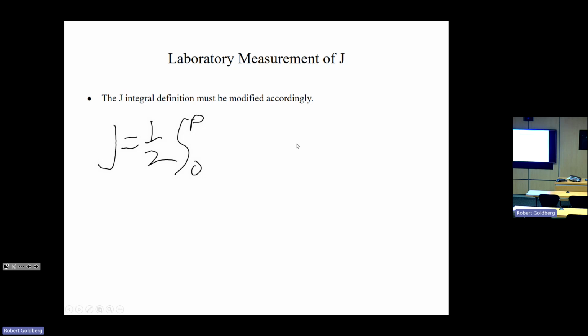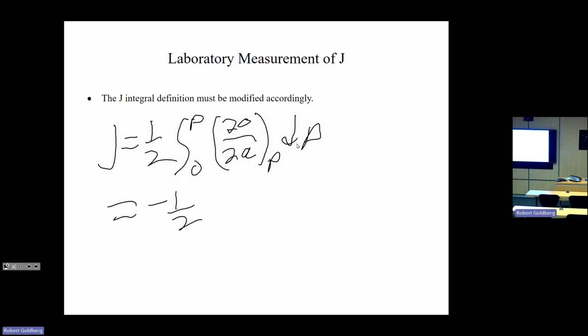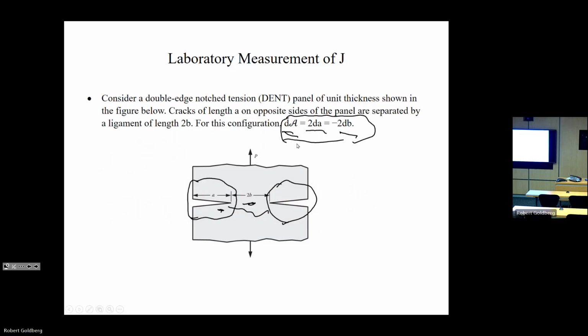So integral from 0 to the current value of applied load of the derivative of the resulting displacement with respect to crack length, for the fact, specifying that we applied the load, and we integrate dP, and we can find that it's equal to -1/2 the integral from 0 to P again of the change in our displacement. And this displacement is all the idea that when you do a fracture experiment, you're usually measuring load displacement curves. So the derivative of the displacement with respect to the distance, half the distance between the cracks, again, all this idea for constant load. And we can do the switch again because of this relationship here.